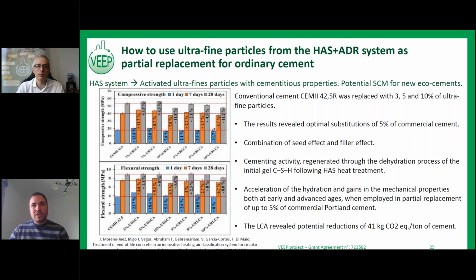But how does it work? What are the effects of the ultrafine particles in the cement matrix? We have detected that there are three main contributions of the ultrafine particles to the cement matrix. The first one is a filler effect. Due to the physical presence of the fine material addition, the specific surface of the cement increases, and we have a better dispersion of the constituents. So we have further nucleation sites for enhancing the hydration process. The second effect is a seed effect. We increase the hydration process by including new C-S-H nanoparticles that act as new hydration nuclei.